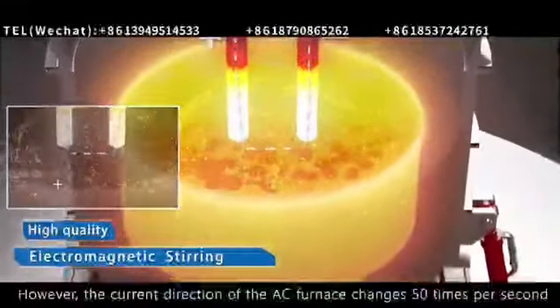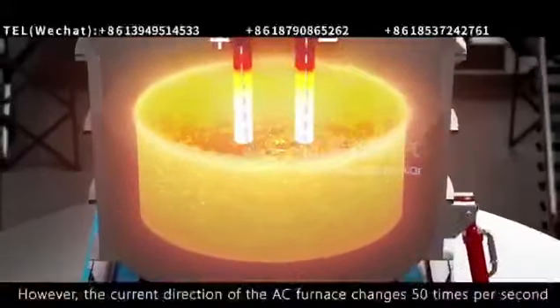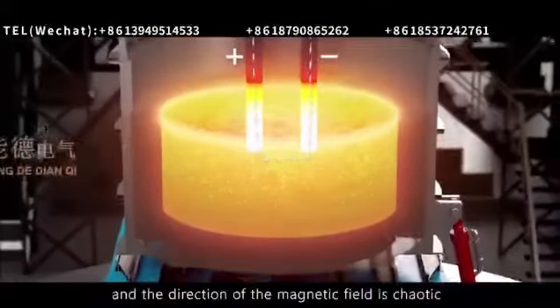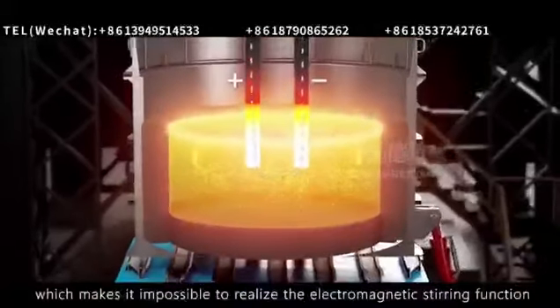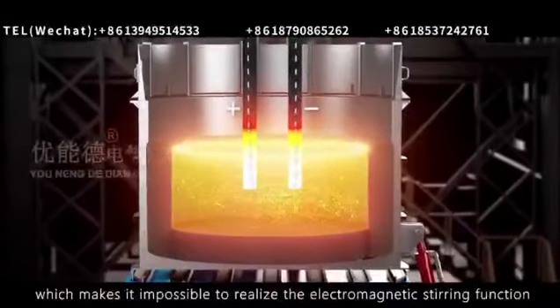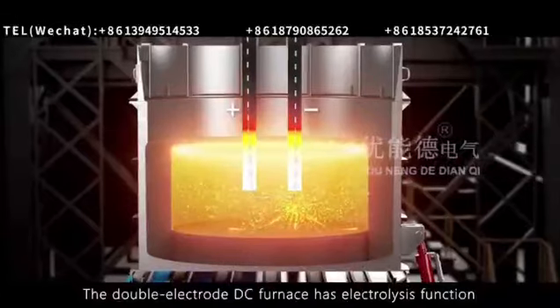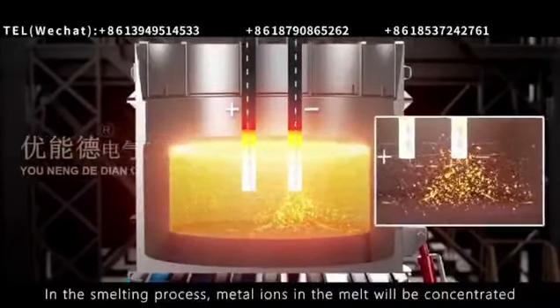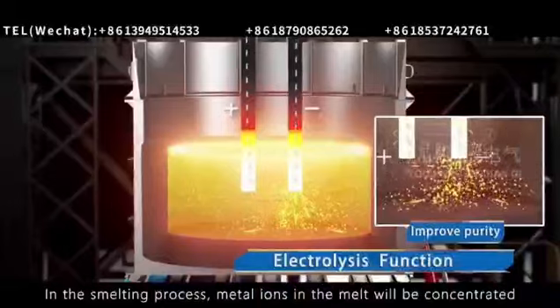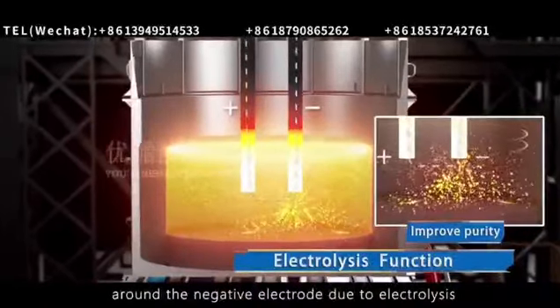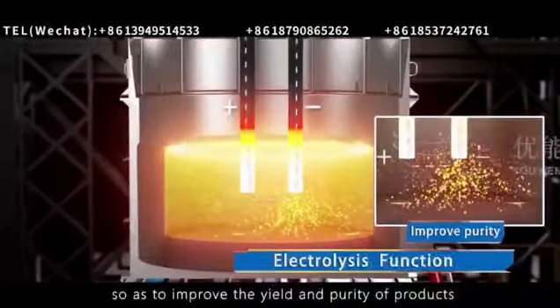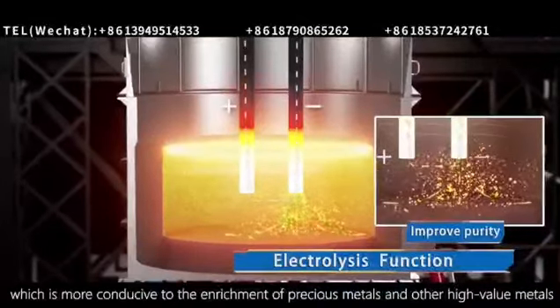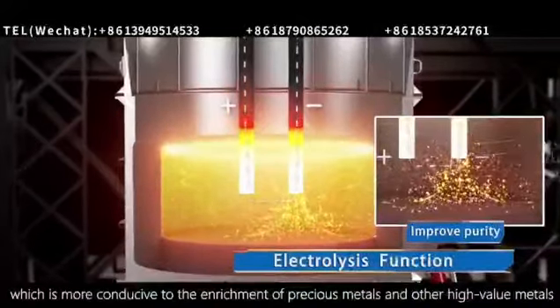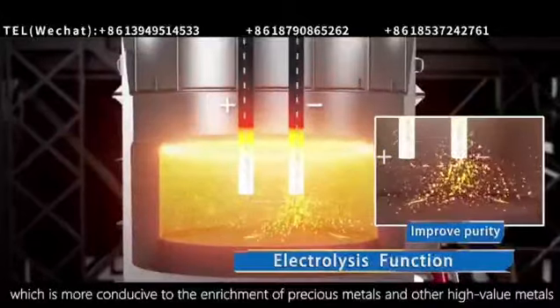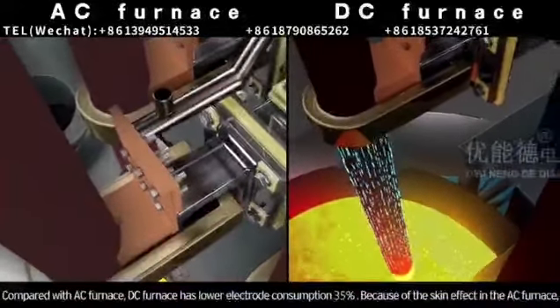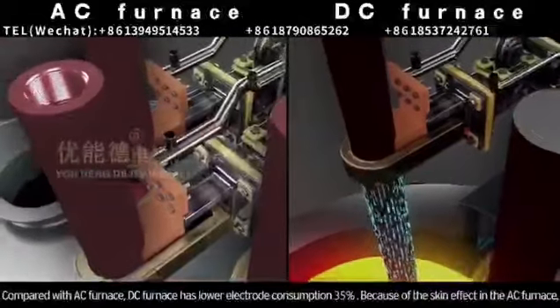However, the current direction of the AC furnace changes 50 times per second, and the direction of the magnetic field is chaotic, which makes it impossible to realize the electromagnetic stirring function. The double electrode DC furnace has electrolysis function. In the smelting process, metal ions in the melt will be concentrated around the negative electrode due to electrolysis, so as to improve the yield and purity of products, which is more conducive to the enrichment of precious metals and other high-value metals. Compared with the AC furnace, DC furnace has 35% lower electrode consumption.